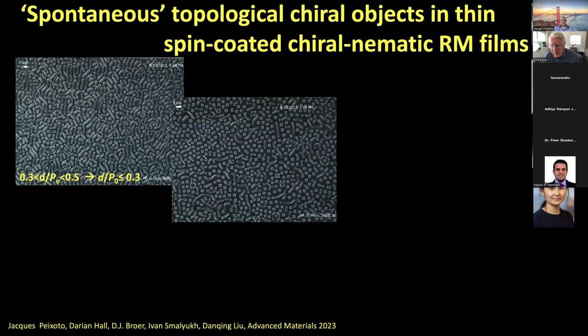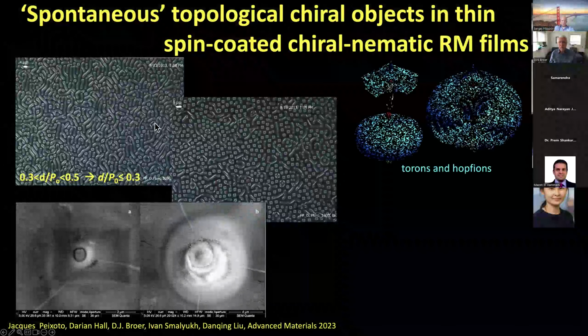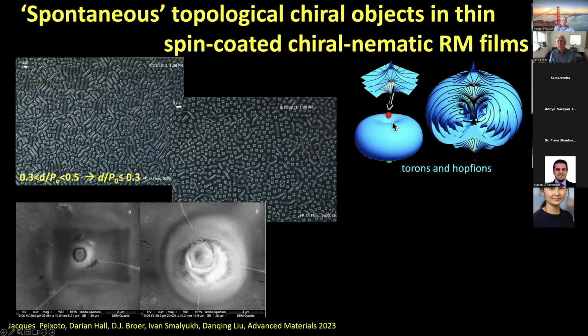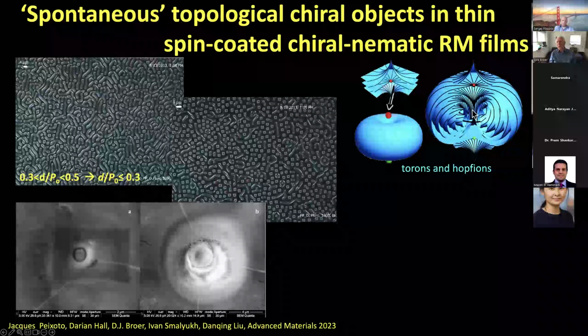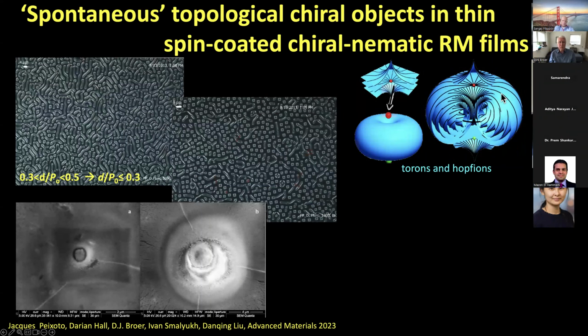I will make now one step to a somewhat more complicated system. So I just discussed the fingerprint textures of the liquid crystals. Well, already in a very early phase, when we started creating fingerprint textures, we saw all these little dots in between the real fingerprints that we want to have. And our first target at that moment was to create conditions to reduce this number of little dots. But later we became more interested in the dots by themselves, and they appeared to be toronic structures where the molecular orientation rotates from perpendicular in the black area to this 180 degrees rotation to the center, and that in all directions.